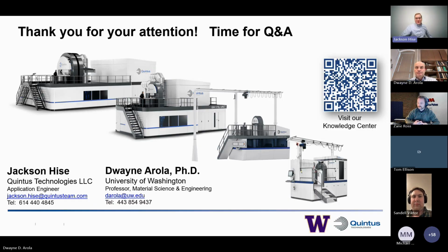Do you have a plan to look at different R ratios? Yeah, another great question. And wow, fatigue just continues to grow and grow in terms of the potential influence of parameters. We have not discussed that in detail, because we're still trying to build the database with the standard R equal to 0.1. It can be something that comes up in the future, but at present we found that the majority of the data that people want, in order to compare their machine to those of the other partners and the growing database, is to develop at 0.1. But again, same thing that was pointed out with regards to higher fatigue lives: the difference in stress ratios can percolate generation of other defects contributing to failure. So it is something that would be worthwhile to discuss and evaluate.